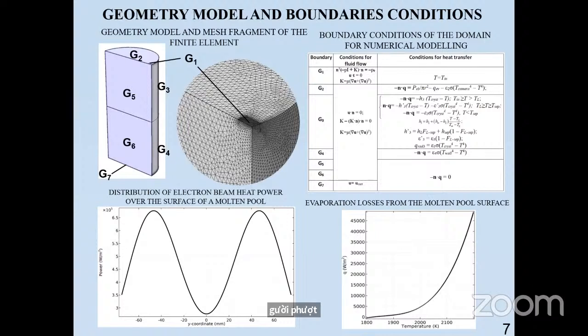On slide 7, the calculation area for the study of the specified process is presented. The boundaries of the calculation area, G1 to G7, are illustrated. Boundary conditions for the presented calculation area are given in a table. The distribution of the thermal power of the electron beam on the surface of the pool mirror varies according to the Gaussian law. The dependence of losses from the surface of the liquid melt due to evaporation is taken in accordance with the temperature.